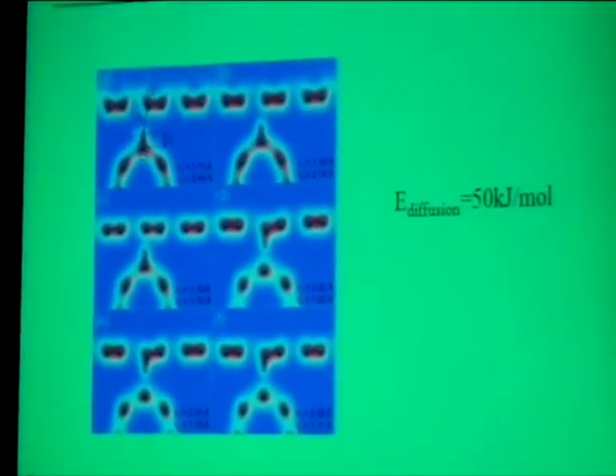So this is why I want to draw everyone's attention: our experiments can show the formation of the hydrogen-carbon bond, and two theoretical groups give explanations. Recently my group did calculations and found that if hydrogen atoms interact with hydrogen molecules, they can form a hydrogen cluster. And then the activation energy is much lower than 50 kilojoules per mole, which makes it easy to move.